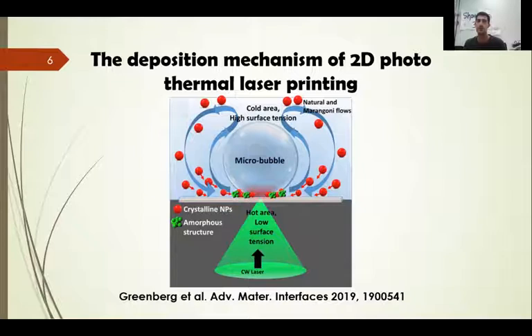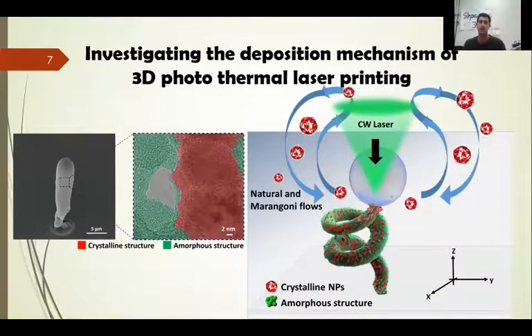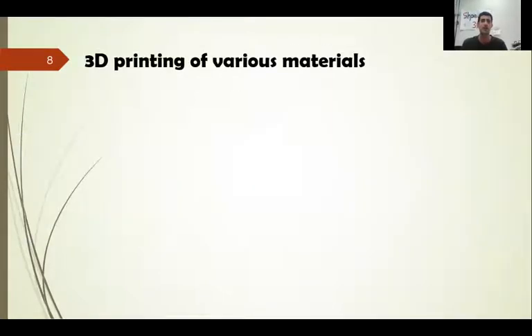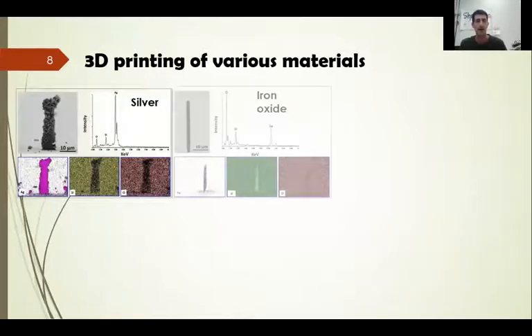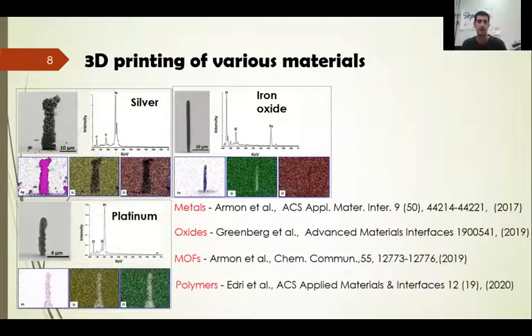Okay, so after we understood what happened in 2D, we wanted to know what happened in 3D. So we also made a 3D structure, a pillar, and we took it to the high resolution TEM. And again, we found that we have a mixture of crystalline and amorphous structure. So we understood that the 3D mechanism is similar to the mechanism in 2D. After we closed the issue of the deposition mechanism, we made some structures from various materials. As I said in the beginning, one of our goals is to develop a new method that could print various materials. So as you can see here, we succeeded in making 3D structures from various materials: silver, iron oxide, and platinum.